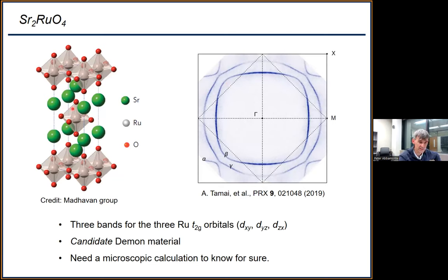So this is a perovskite. It's basically a stack of ruthenium oxide layers separated by some strontium atoms. It has the same crystal structure as some of the high temperature superconductors, but it's actually a low temperature superconductor. Tc is about 1.5 Kelvin. And what's intriguing about strontium ruthenate is two things. The first is that it's actually a very nice Fermi liquid. So it has really long-lived quasi-particles near the Fermi energy. And if you measure the resistivity as a function of temperature, it has a nice T-squared form. So it's very well-behaved, has nice, well-defined oscillations in Shubnikov-de Haas experiments. So it's really just straight out of the textbooks.